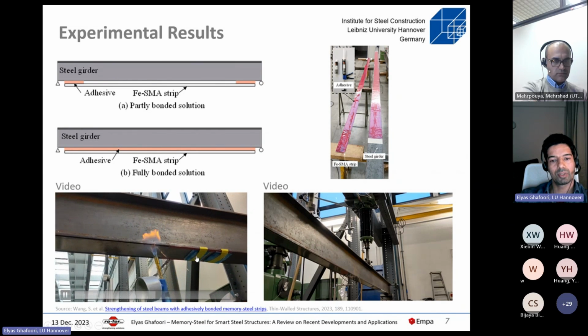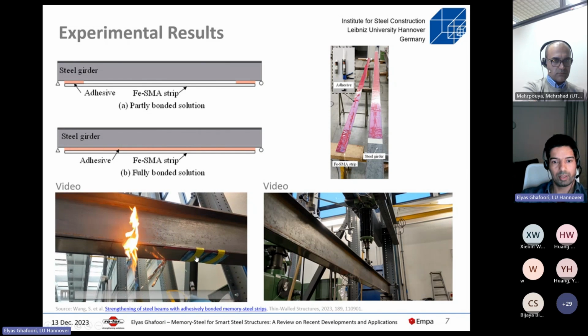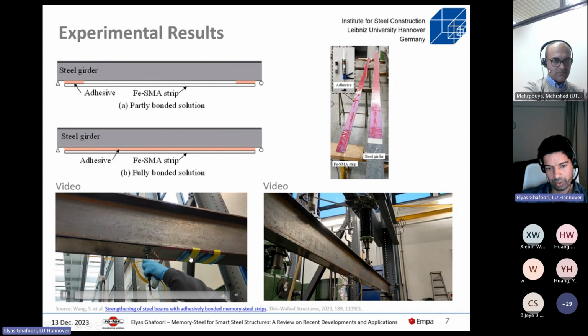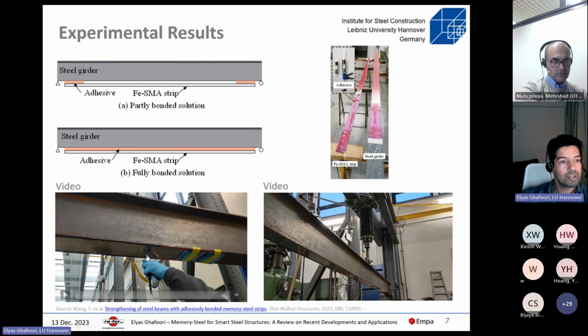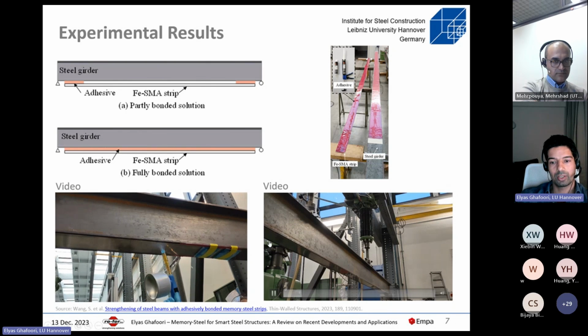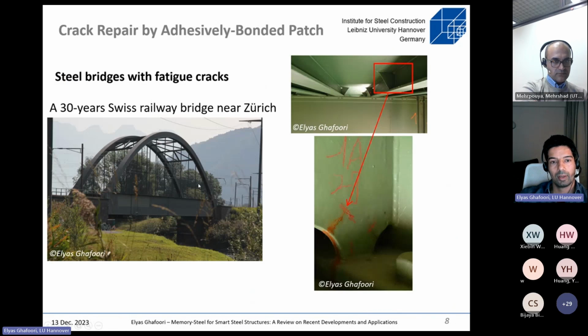You see here we put some ice pack to keep the anchors cool, and then using a thermocouple, we measure the temperature to make sure that we have the right temperature for activation. And of course, afterward, we did fatigue tests, more than 2 million cycles, and a few beams, not only one beam, to make sure about the structural integrity of the system. So this is one application.